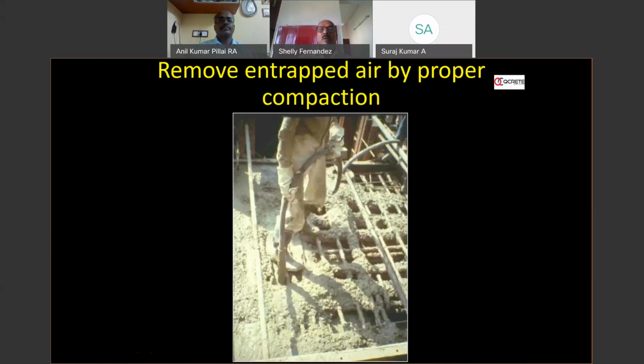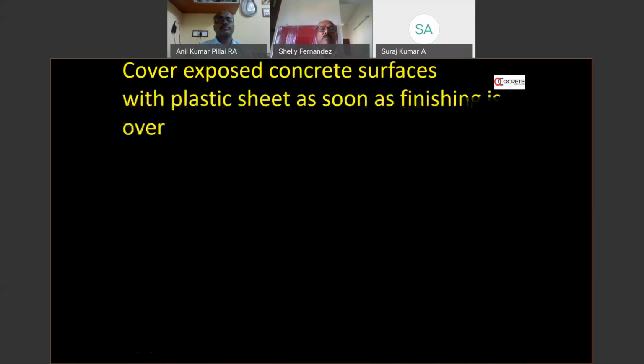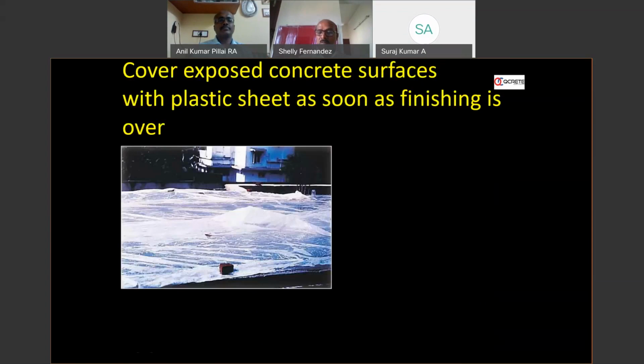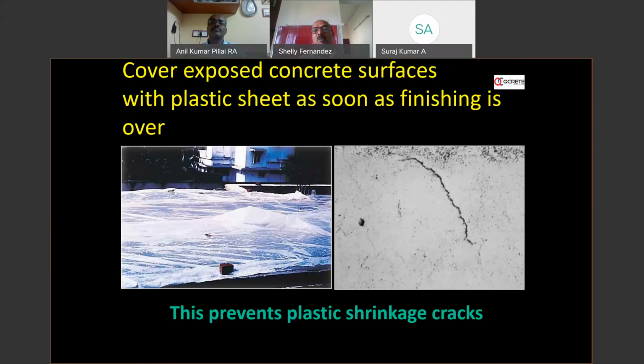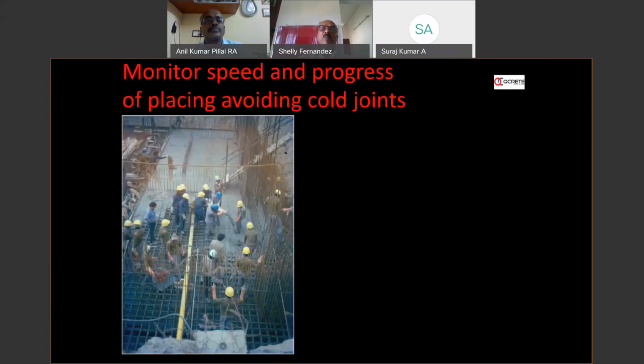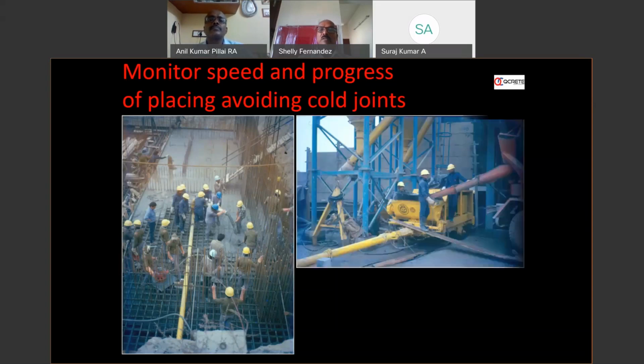Again, you can remove all voids by proper compaction. That is why you have to have sufficient vibrators at site to do proper compaction. And then cover it with plastic sheets. As you know, ready-mix concrete is different from site-mix concrete. In site mix, the rate of concreting is very low. We keep on finishing it, so we are disturbing the surface and there will not be any cracks appearing. But for ready-mix, we finish the job in 2 or 3 hours and we leave, and we end up with shrinkage cracks. So the best is to cover it with plastic sheet or start early curing by sprinkling water on it. So, monitor speed and progress of placing concrete, avoiding cold joints.